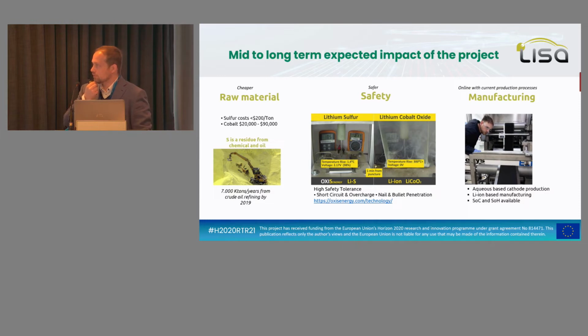Regarding the impact, as you know, this slide has been done before the conflict with Russia. You know that today nickel is more than 100,000 euro per ton. Basically, it is more expensive to transport sulfur than to buy sulfur. We know that from the 90s, we have always had some issues regarding the supply chain. In the past it was cobalt, with unstable regions, and today it is nickel. Since then, we have always been depending on someone somewhere. Sulfur is coming from Europe, is a waste from the oil industry and the chemical industry, so we have plenty of sulfur. On the cathode there is only sulfur and carbon.